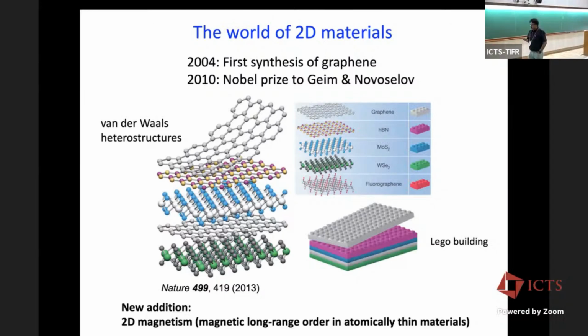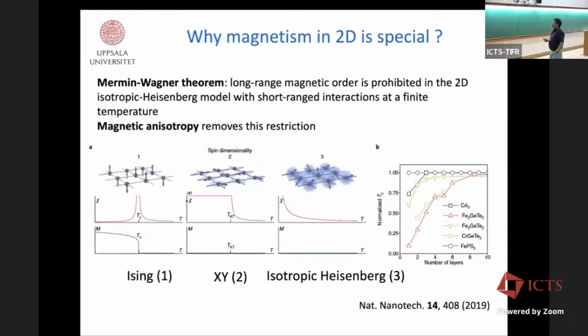A new addition, two-dimensional magnetism, is only a few years old: magnetic long-range order in atomically thin materials. That's the key word actually. And we also heard about the Mermin-Wagner theorem. I don't have to repeat that. Magnetic anisotropy is the key thing here. In all these systems where we see a magnetic long-range order even down to a monolayer, the magnetic anisotropy plays an important role.